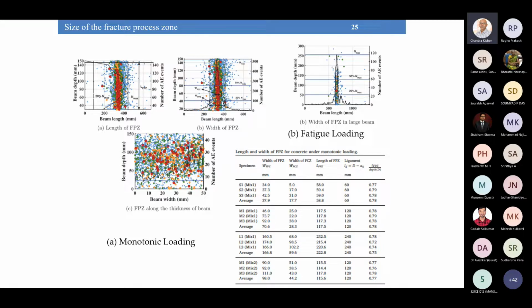See, under monotonic loading, we could see the development of the fracture process zone. We have computed the width, the length, and the depth. And also another interesting thing is the ligament length. So when we normalize the length, the width, and the thickness of the fracture process zone with the depth of the specimen, we get a constant value of almost 0.78 or 0.79. For different sizes and different concrete mixes, we see a constant value of the size of the fracture process zone normalized with the depth. So what it means is we can use this as some kind of a material property, some kind of a characteristic length, which is used in most of the nonlinear models.